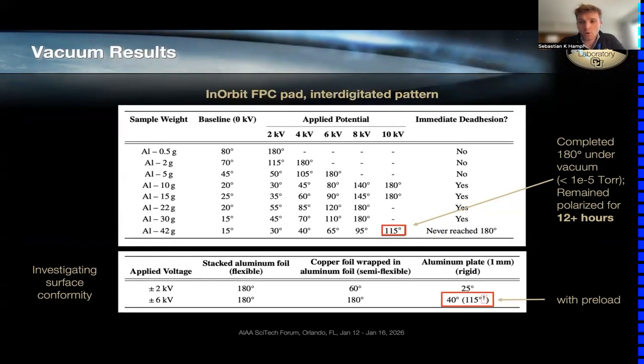We recorded the results for these experiments in the following table, where we had different samples, in this case aluminum, of different weights, ranging from 0.5 to 42 grams. First, we baselined the performance, meaning that we just placed the sample onto the electroadhesion pad and rotated to see how much natural friction force there is between the pad and the sample. As one can see, the lighter samples require way less voltage to complete the full rotation than the heavier samples.